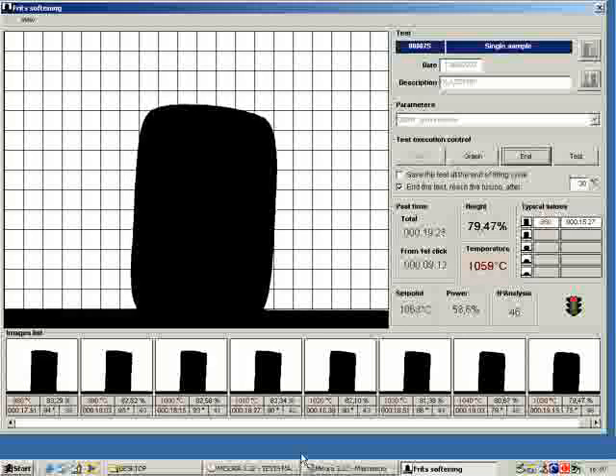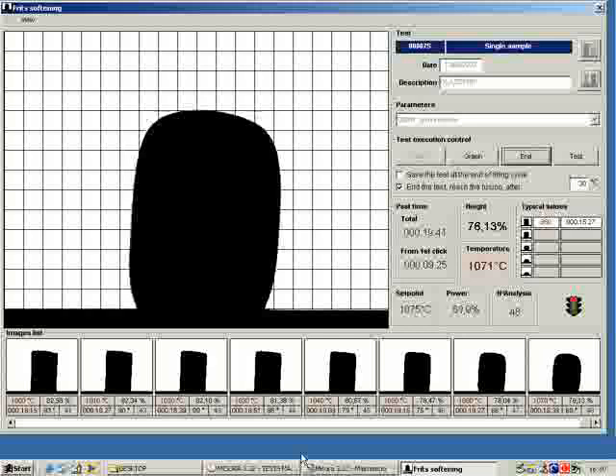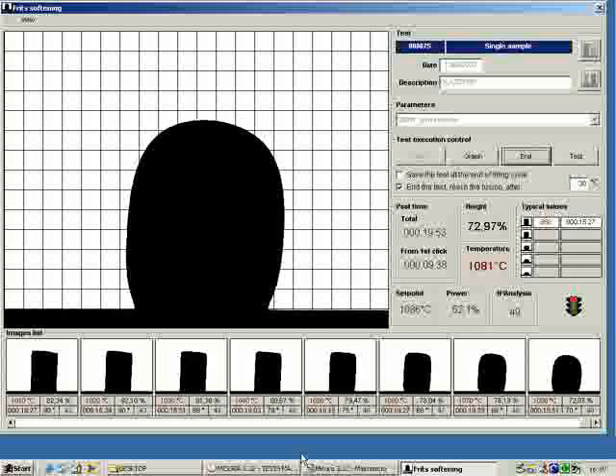The shape of the sample is changing because the material is becoming liquid, and the surface tension is trying to reduce the surface of the sample to the minimum. At 1100 degrees, the material is completely liquid and the shape of the sample becomes spherical. In order to get the sphere shape, the sample must be very small. In this way, the hydrostatic pressure, which would flatten the drop of liquid, is negligible compared to the surface tension.